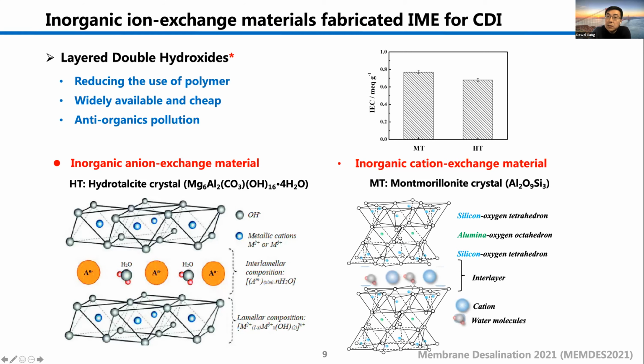In nature, some natural materials and clays have also shown ion exchange capability because of their multi-layer nanostructure, like LDH, layered double hydroxide. For example, hydrotalcite (HT) is composed of a positively charged main layer and anions in the interlayer, so the anion can be stored and exchanged. On the other hand, MT, montmorillonite, can store cations in the interlayer. So these two materials maybe could be chosen as ion exchange materials.